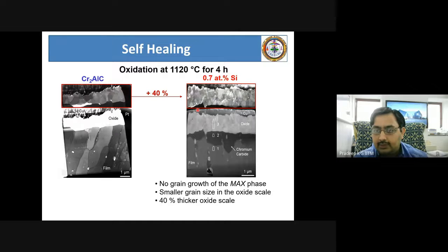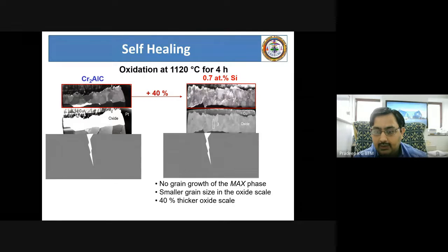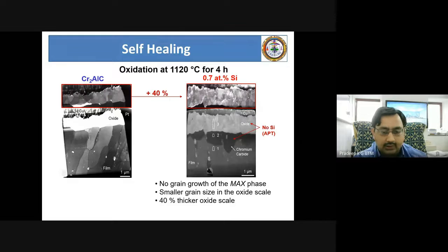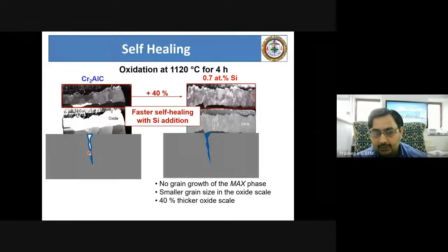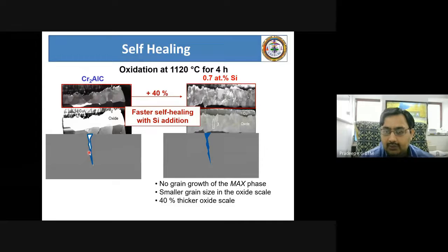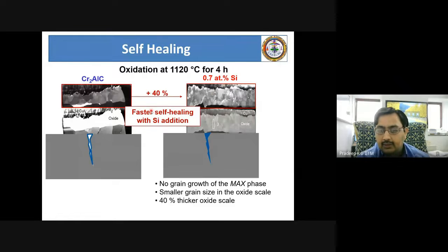The layer thickness improves by 40% compared to what you have in the absence of silicon. That means when you have a crack as deep as this, in the presence of silicon, you're going to fill this crack much faster than what can happen in the absence of silicon. That means the concept of self-healing works when this kind of unique combination of materials having ceramic and metallic properties works together. At the same time, the kinetics of self-healing can be activated by alloying certain species so that the region or depth of the crack can be healed at a much faster rate.